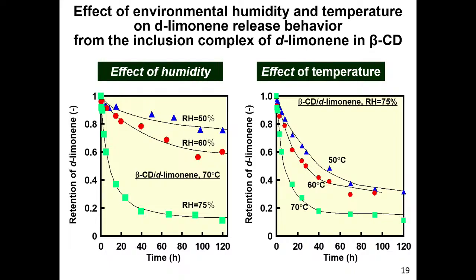So this is the effect of humidity. High humidity condition, we can see the high release rate. So when we want to see the release, we need the moisture.